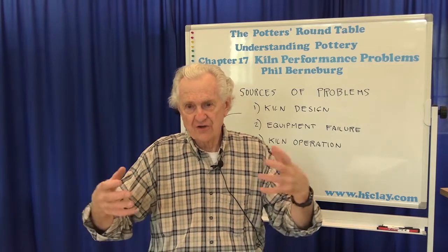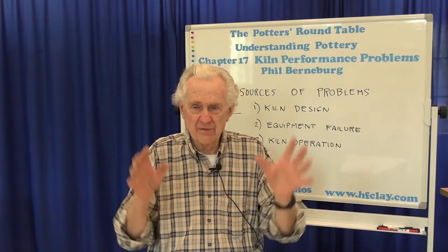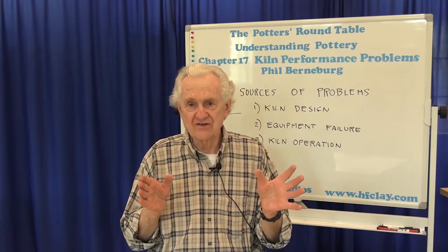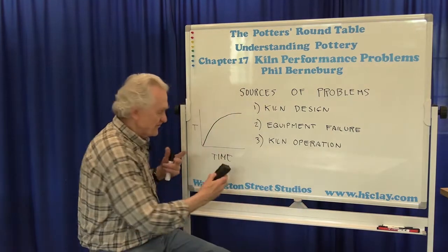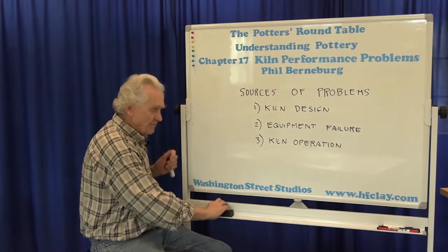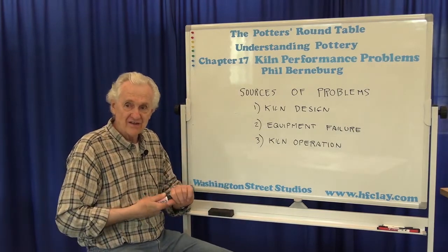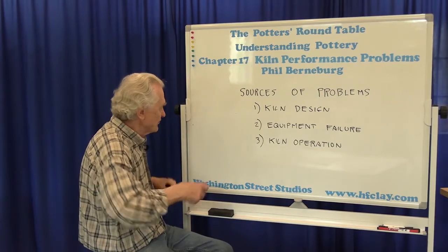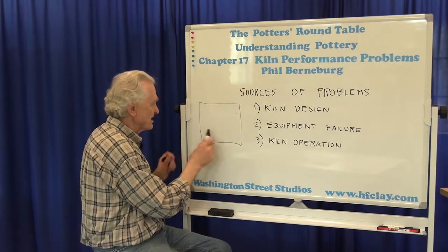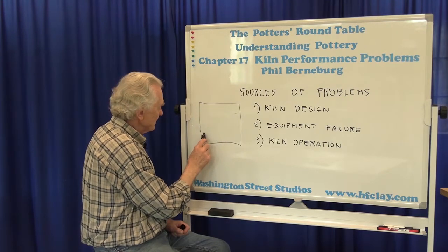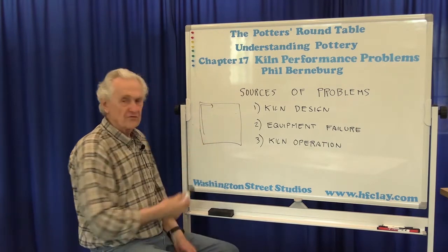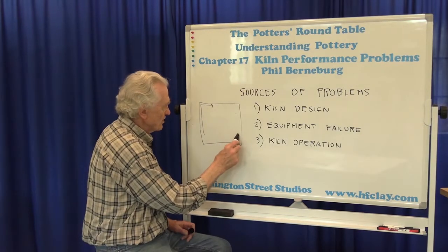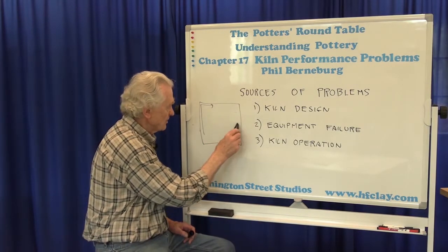There could also be what are commonly known as dead spots in the kiln, and that is where the shape of the kiln or the location of the burners creates spots in the kiln, typically corners, where the flame simply does not go into the corner and heat it up. There's an awful lot of wishful thinking in pottery, where people think that because something should happen, it does, but it doesn't. So it's very common, if I look down, for instance, at the top of a kiln, there's no reason for a flame to go into a corner and turn right and do that. It's basically a blind corner, so the flame is more likely to want to do that.